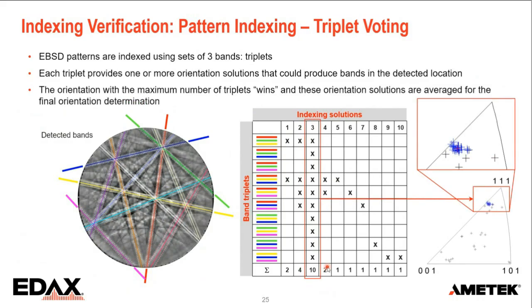Then we do it in a very democratic way. We just count the votes for each solution, and the solution with the highest number of triplets wins. But that's not where it ends, because each triplet has its own orientation solution with it. So that means if we show that in an inverse pole figure, you get a little cluster of points of orientations that belong to orientation number 3, and the final orientation that we save is the average of those. And that makes it extremely sensitive to a very good orientation precision, even if some of the bands may be slightly misidentified. It doesn't really matter.